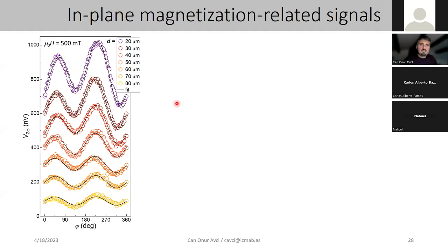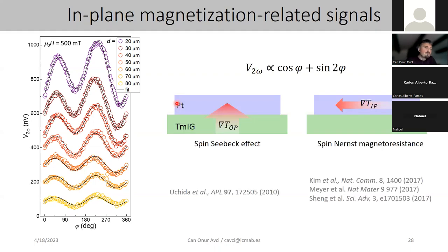But after analyzing, we were able to find out that it's coming from two different elements. The first is this cosine phi behavior, and that is due to the spin-Seebeck effect, which is purely a spin current pumped from the garnet into the platinum by thermal excitations, thermal magnons, and that is converted into a voltage by the inverse spin Hall effect.